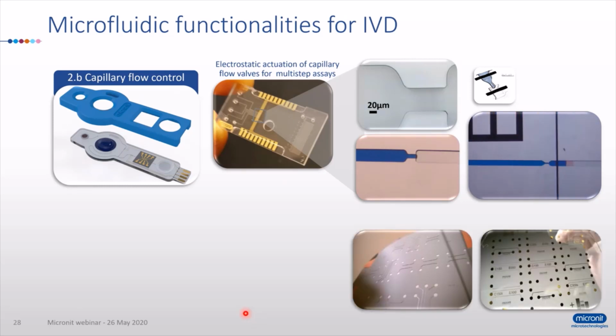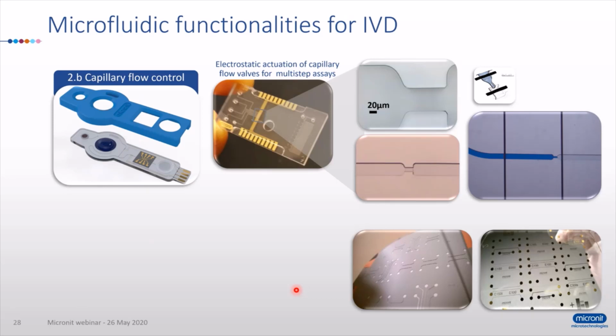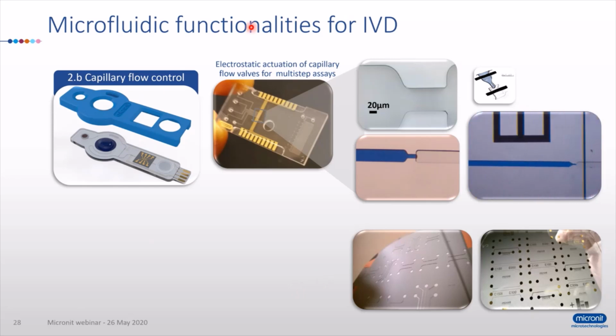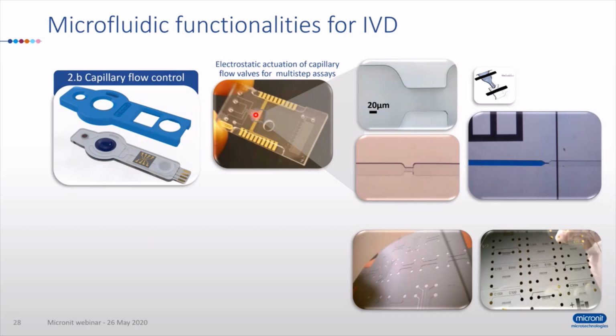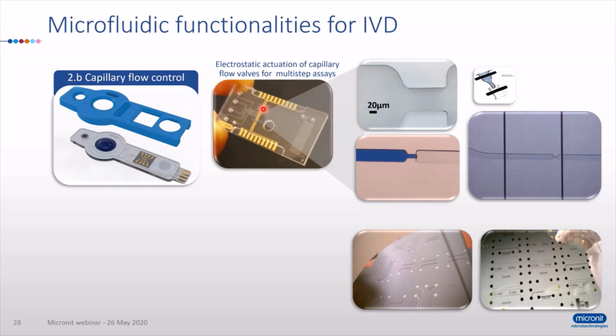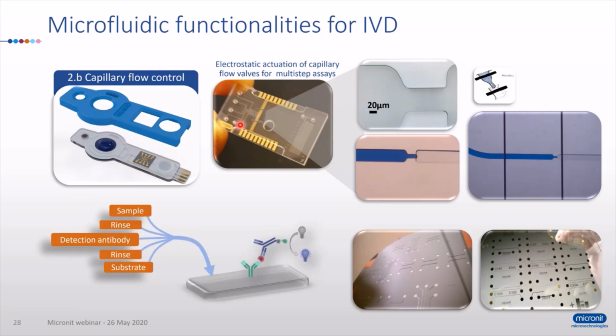As I already mentioned, we fabricate these kinds of devices by embossing. So we have an embossed layer, we have a layer which is patterned with electrodes. We bond them together, direct bonding without adhesives, and then after singulation we get this kind of devices. So as you see here, we have a number of incoming channels. Each of these channels displays one of these capillary valves, each of them with their electrodes for actuation, and this can provide sequential flow that can be used, for example, for running an immunoassay, adding reagents sequentially.